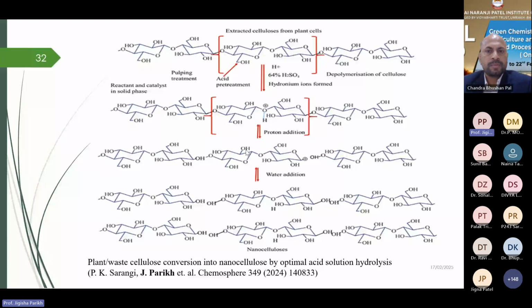It is very much disordered and readily breaks only if heat treatment is given, or the cellulose chain, which is densely packed, we have to loosen that structure and then further depolymerize. So overall we can say that acid pretreatment uses hydronium ions to attack and break down intramolecular and intermolecular bonds in this biomass hierarchy structure of hemicellulose, cellulose, and lignin to disassemble the complicated structure of this biomass resource.